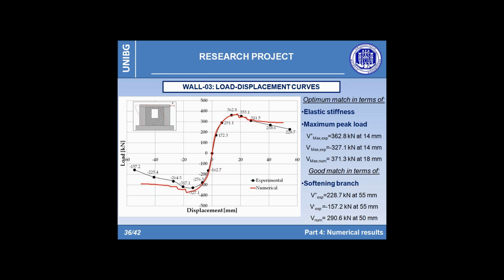The trend of the softening branch is representative of the real structural behavior. However, it's interesting to note that the slopes of the two degrading post-peak branches tend to slightly diverge. The reason for this trend may be related to the greater damage suffered by the structural walls due to the stiffening effect exerted by the infill portion coinciding with the spandrel under the window. This configuration tends to reduce the slenderness of the walls, thereby inducing high shear stresses.